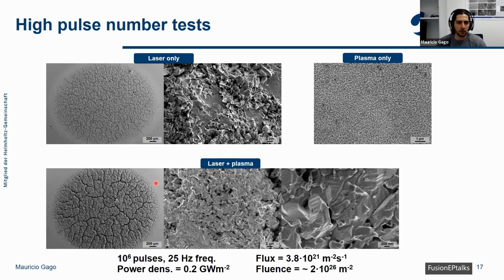So also due to time limitations, the frequency of the pulses had to be increased, and because of this, if a higher power load was applied, the temperature of the samples would increase way too much, even the base temperature. So this wouldn't have been able to stabilize. And then a power density of only 0.2 gigawatts per square meter was used. So only the lower power density that has been used up until now for these high pulse number tests.